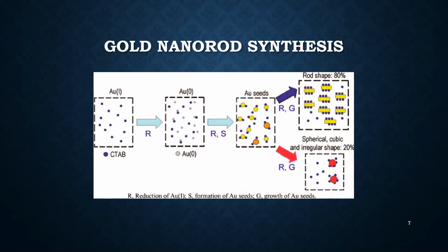This deposition slows down the growth rate of the crystal facets, giving the orientation to one-directional growth and formation of rods. The high uniformity synthesis in this article involves adding silver ions to the seed synthesis, which helps with one-directional growth from the beginning, resulting in rods instead of sphere formation in the seed solution.